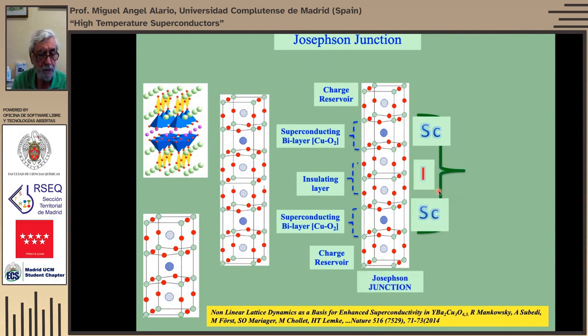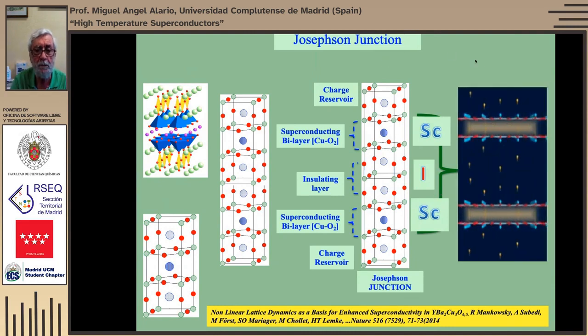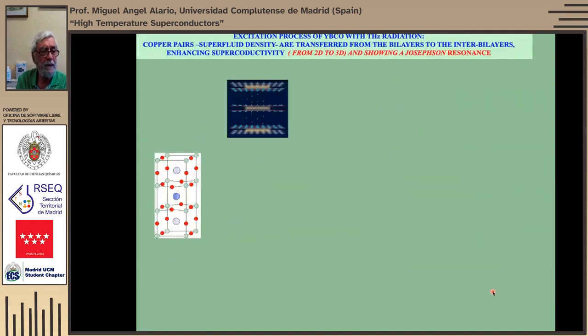So this is a Josephson junction, which is the thing that actually gives this Josephson resonance. So the electrons can actually travel. You can see that better in the original drawing of Cavalieri's group. So that will be the superconducting bilayer here, and this is the other one, and this is the insulator. So that's the Josephson junction. So in normal circumstances, there is no connection between here. Very little, even if you put an electron current here, it doesn't go, or it doesn't superconduct. But then if you make the pulse, then things change.